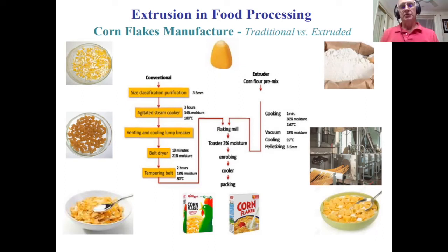On the other hand, we can take those same corn grits and put them through a roller refiner and produce maize flour. Now, the maize flour can be put into an extruder and operated at similar moisture contents, but much higher temperatures. And we're able to produce a cooked corn mass that we can see coming out of the die assembly here. Those ropes of cooked corn are too sticky to be directly cut, and so we're taking them offline, cooling them partially before cutting them, and then those individual pellets can be sent through the flaking mill to form corn flakes.